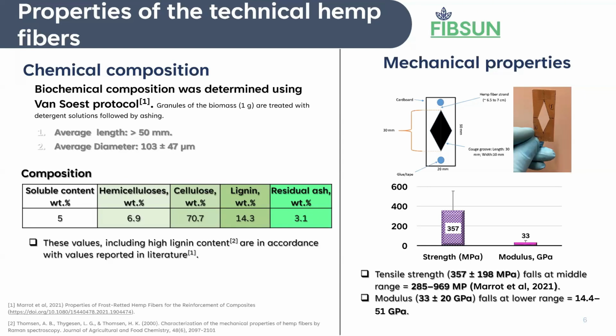And so here we give a basic understanding of the chemical composition of our fibers. We did this with a method called the Van Soest protocol. This protocol helps us understand the composition of soluble content, hemicelluloses, celluloses, lignin, and residual ash. The main goal here is that this composition influences the properties of the fibers and how the fibers will behave in application. So we found that the results are not so different from what we already know from literature. Of course, the lignin content in these fibers was pretty high, but also in literature, we found some results with up to 13% lignin content.